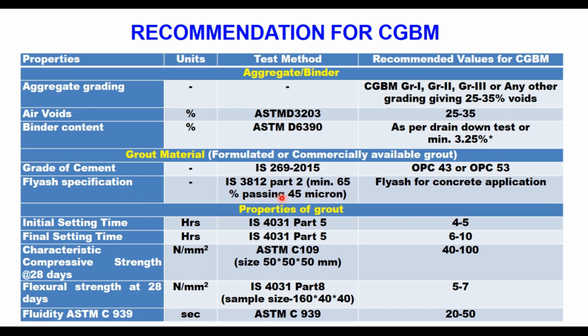The initial setting time of the grout should be 4 to 5 hours and the final setting time 6 to 10 hours. The characteristic compressive strength of the grout should be 40 to 100 Newton per millimeter square, and flexural strength 5 to 7 Newton per millimeter square, and fluidity, as measured as per ASTM C939, should be 20 to 50 seconds.